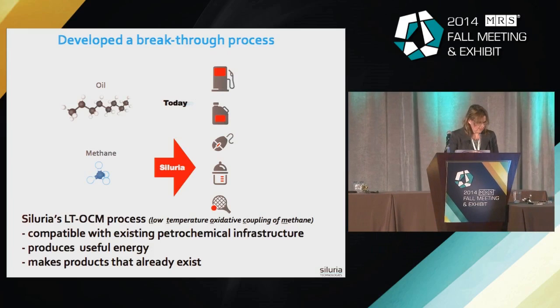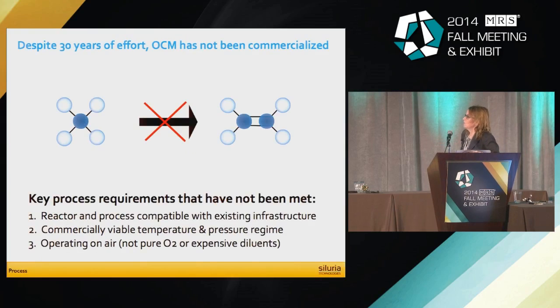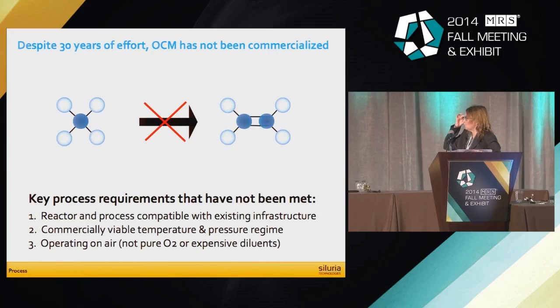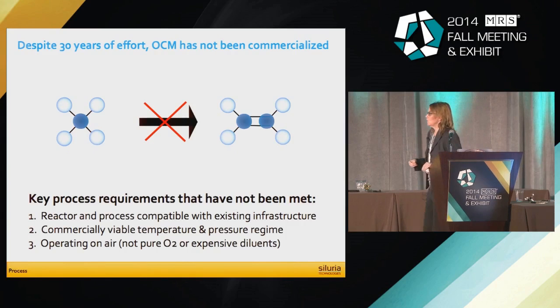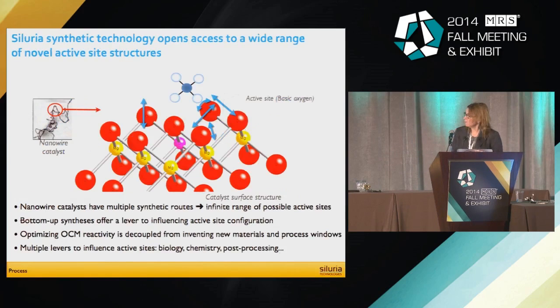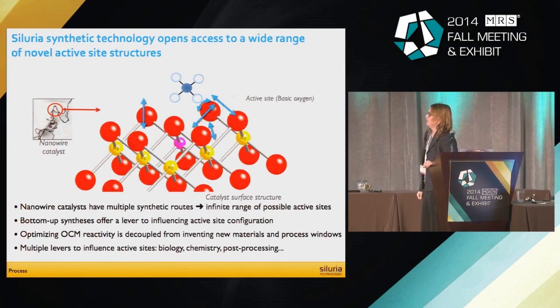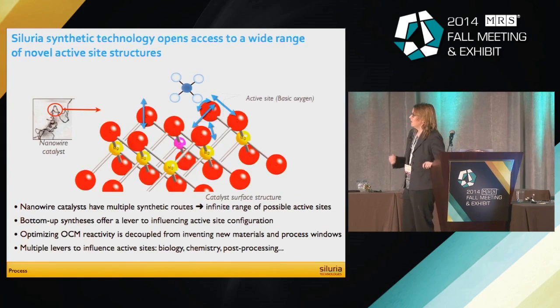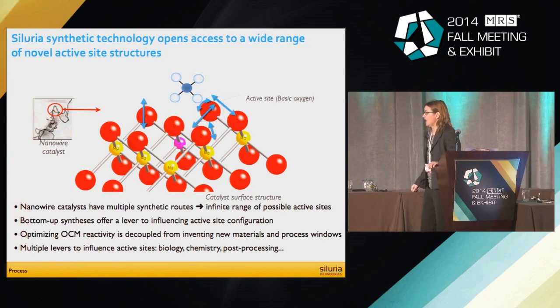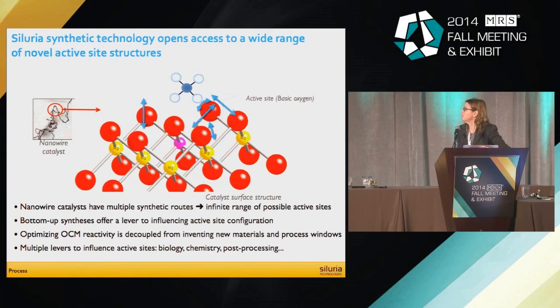And so we had a great team of scientists that came on board and worked on this. It's a very difficult process. People have been trying to work on how to do it economically, at low temperature, for about 30 years, and hadn't been successful. And so we said, well, what if we let biology work on it and see if biology can help solve the problem? And so what we did at Siluria was take combinatorial chemistry, combinatorial biology, and rapid throughput screening to see if we could find new catalysts for this reaction. And we were able to find nanowire catalysts that were made of a combination of different elements, and we were able to find about 10 catalysts that were effective in this reaction, and with a 60% lower carbon footprint.